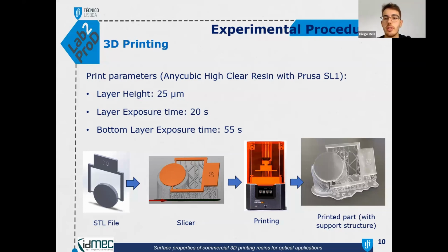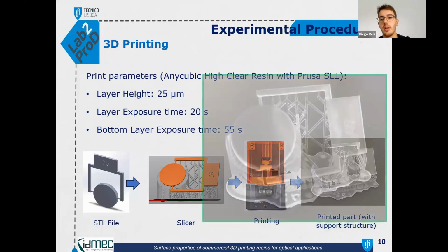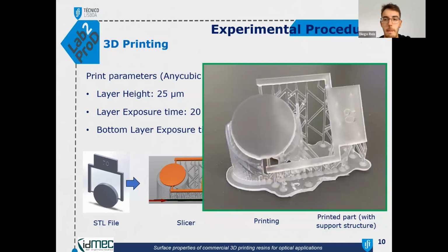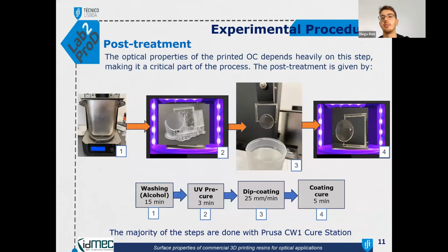We used 25 micrometers with a layer exposure time of 20 seconds for this resin, which was a bit higher than the other ones that we tested. Here is a zoom of the printing, and then the post-treatment, which is the critical part of the process, because it will give the final appearance of the lenses.